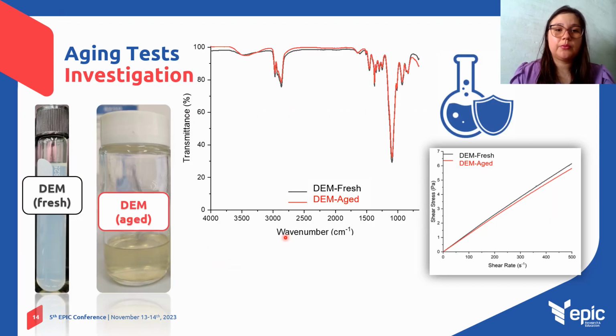This slide shows the emulsifier before and after the aging tests, here named fresh emulsifier and aged emulsifier. There is no significant alteration of its visual aspect, besides a light yellow coloration for the aged sample, with no detection of solid precipitates, showing that there is no alteration in the emulsifier properties and that it is stable for long periods at the injection conditions. Its rheological behavior remains that of a Newtonian fluid, and its infrared spectrum does not demonstrate chemical degradation after